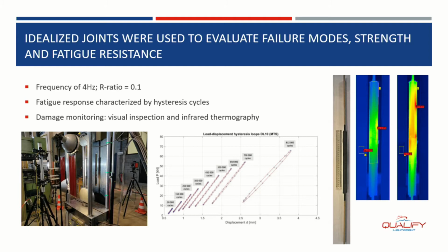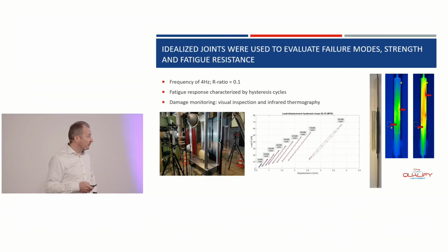All tests were performed at 4 Hertz, the maximum frequency we can reach to avoid that there would be any self-heating in the adhesive, and as a result, maybe differences in damage evolution. Tests performed at an R ratio of 0.1.